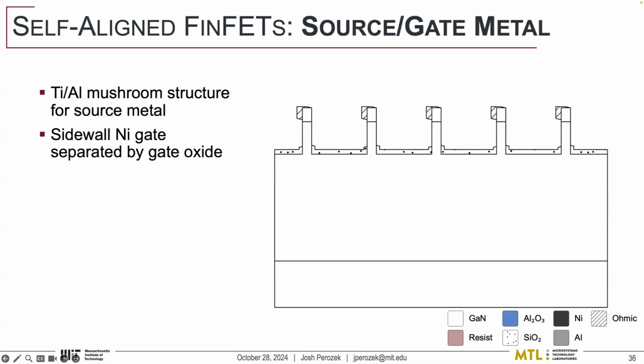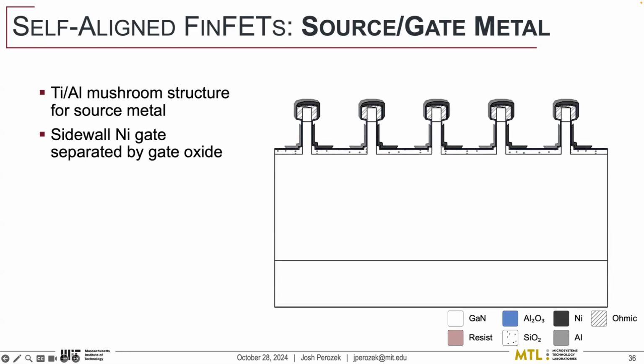To keep making the FinFET, we can do a source first process. So now before we put the gate metal on, we can put the source. Same exact mushroom structure that we had before, using our Ti/aluminum as ohmics. We align that to an N+ region on the GaN to make nice ohmic contacts. And now since it's a source first process, we can then make the gate. So we put down our gate dielectric. We do the same thing with the nickel. We use nickel because it has a beneficial work function offset with the gallium nitride. It lets us increase the threshold voltage.